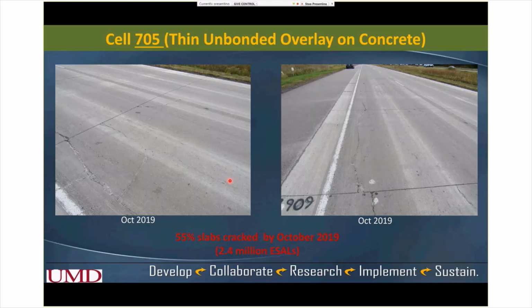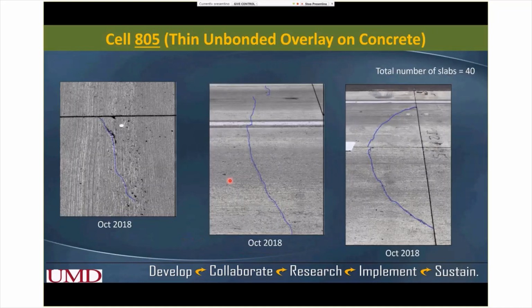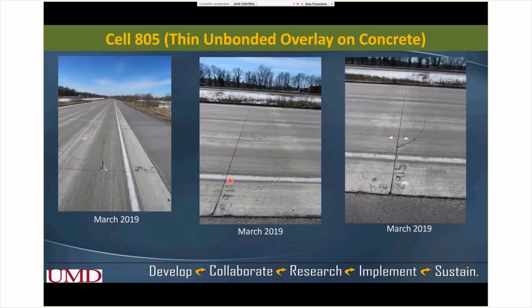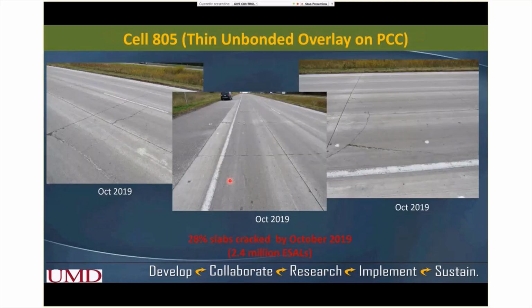Cell 805, which had narrower slabs, also saw transverse, longitudinal, and corner cracks. And those also increased, but these slabs did not crack as much as cell 705 had. So 28% of slabs cracked by October 2019 at 2.4 million ESALs.